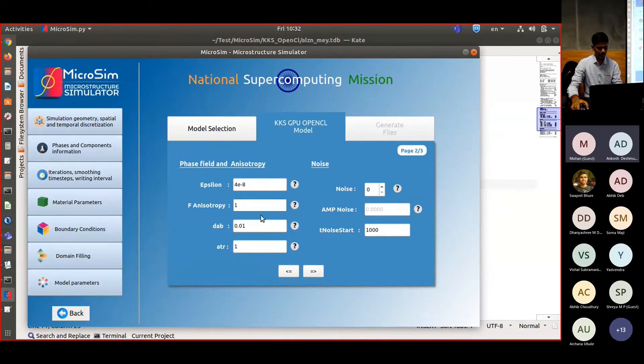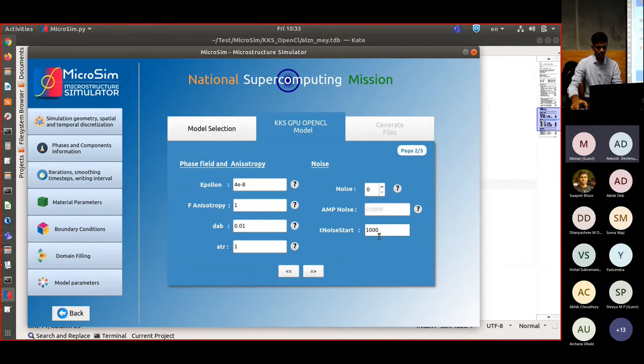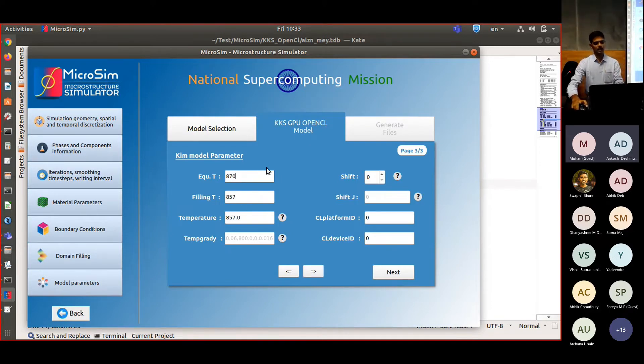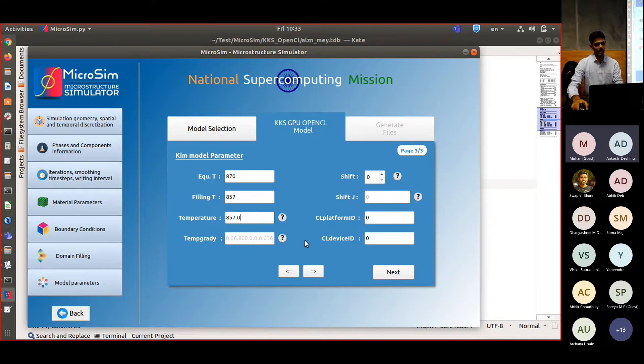We are going to use fourfold anisotropy with a strength of 0.01. The anti-trapping parameter is enabled and noise is kept at zero, so it won't affect the simulation. The equilibrium temperature for the system is 870 K, the filling is done at 857 K, and the simulation temperature is 857 K, corresponding to 13 Kelvin undercooling. We are doing an isothermal simulation so the temperature gradient is disabled and the shift is zero.